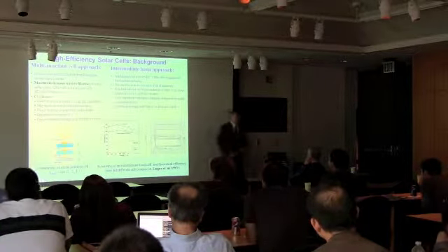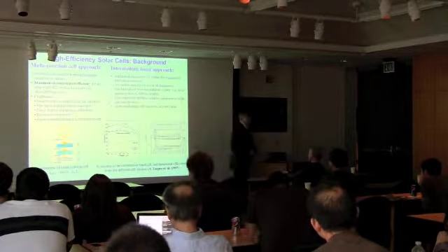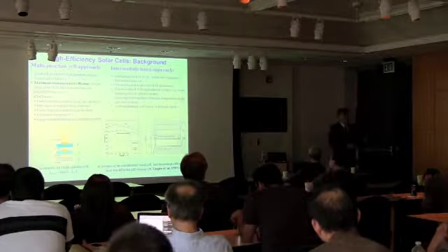You increase the absorption, but quantum mechanically absorption of this photon and emission of this photon have the same probability, but it might also be thermal absorption of an electron from here to there, and the same for holes from there to there. So by putting in additional dots, creating this very beneficial additional harvesting, you create additional recombination centers. If you remember the Niagara Falls example, you create some kind of holes inside of the river. They are invisible and water can go there.